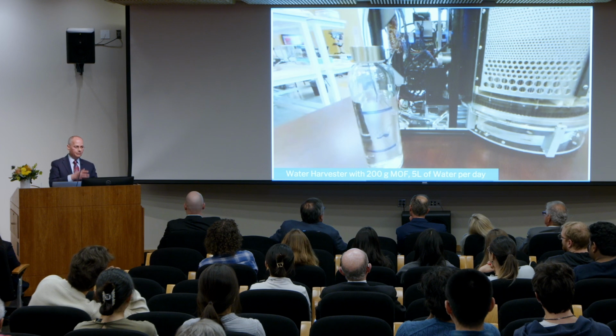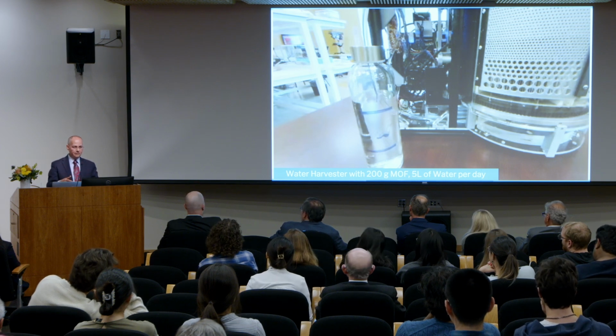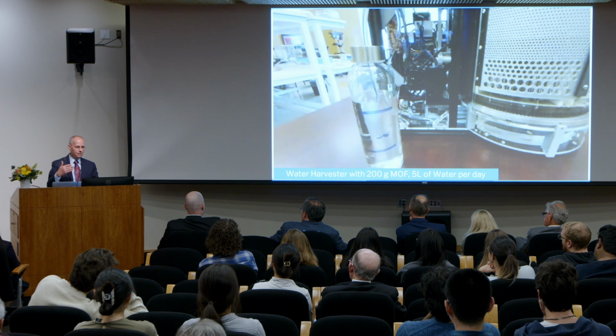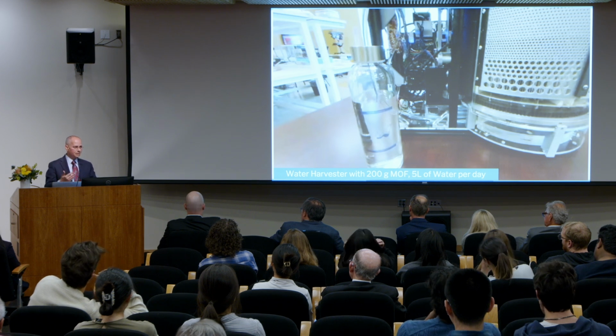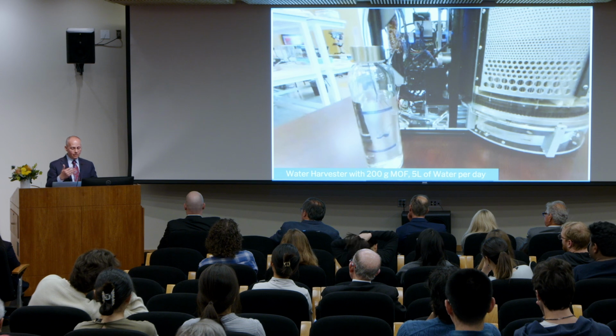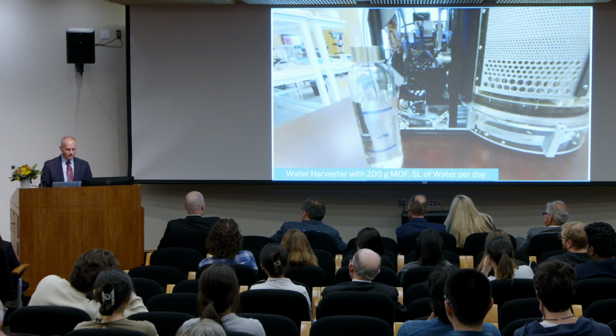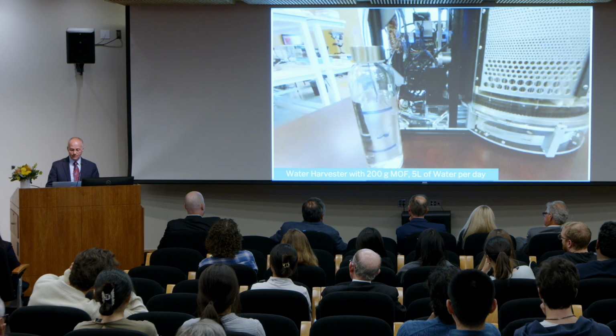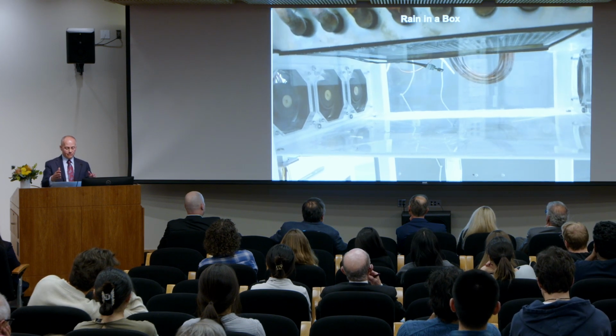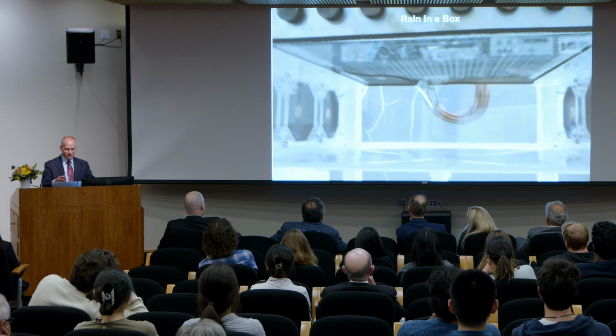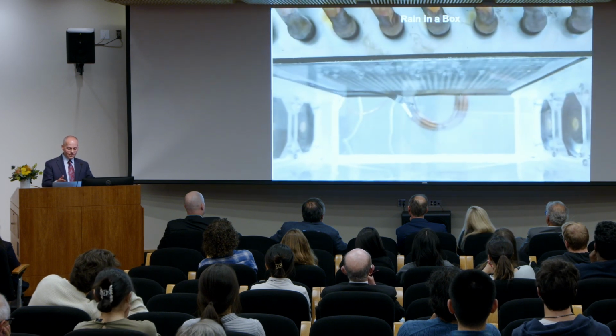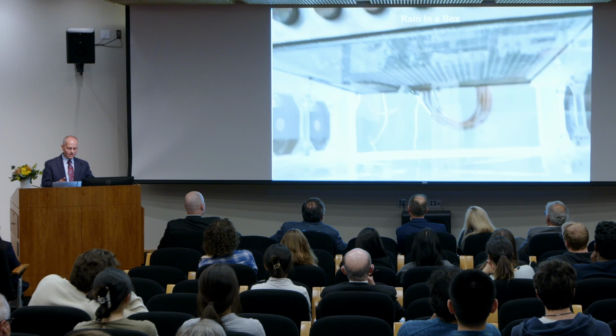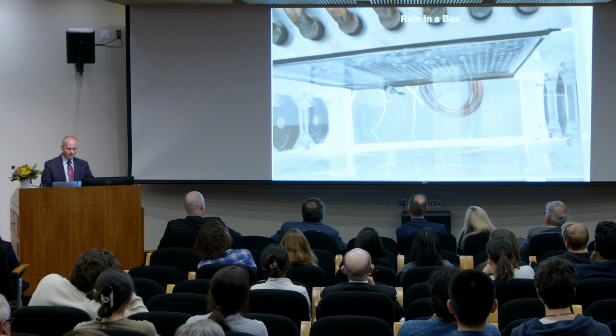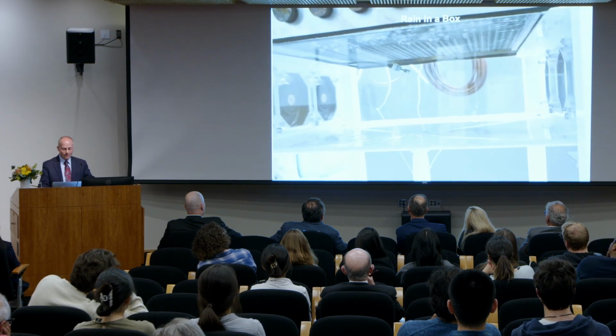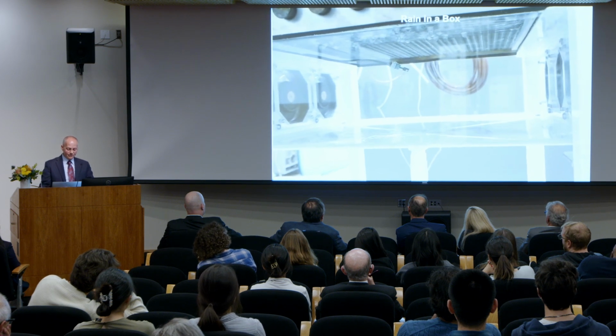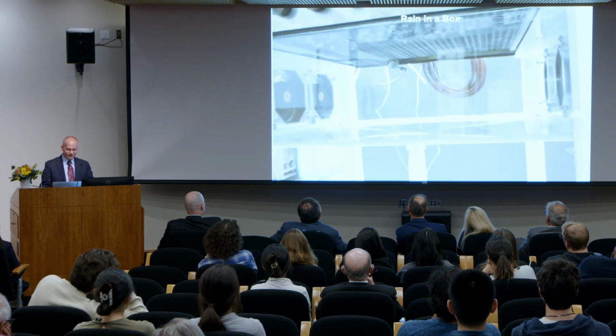So we have been going through one prototype after another, improving the placement of the MOF in the device to expose it maximally to air. And we have also been looking at the energetics of the system, especially for the electrified device, to make sure that they are also energy efficient. This is not a very good video, but I call it the rain in a box. This is the same MOF, but you can see that you can collect water, more rain coming out of the MOF.